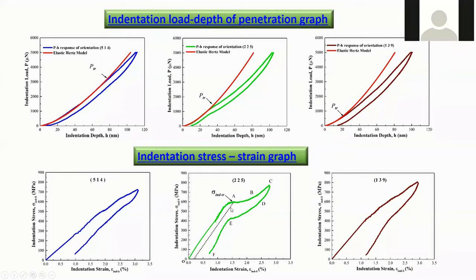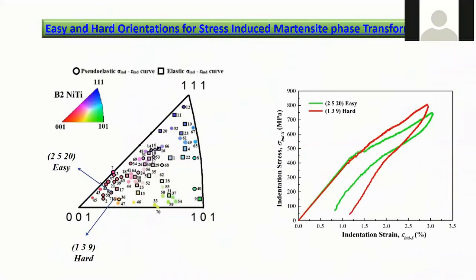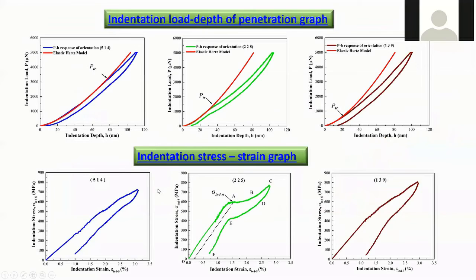And you can see that one of the grains here shows a very nice pseudoelastic pattern in comparison to others, which show a very high plastic deformation part. So we would like to avoid such grains which are giving us plastic deformation, and we would be happy to work on something which is giving us pseudoelastic deformation. So this is how we figured out the easy orientation. Easy means the one which can convert to pseudoelasticity very easily, and hard means one which is not pseudoelastic. So we also found out the recoverable strain.